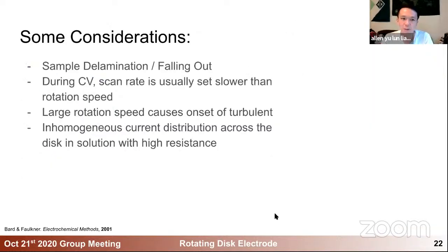So if you decide to use RDE in your setup, whether it's for aqueous or non-aqueous electrolyte, there are some considerations you have to be careful about. For example, if you decide to drop cast your active particle material on the electrode surface, make sure that the material can stick onto the electrode surface well using some binder or any method, so the material would not fall out or delaminate from your electrode surface while you're spinning it.